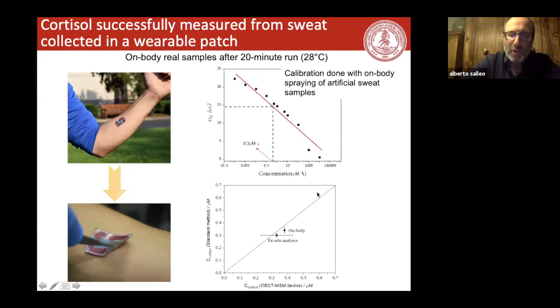And then he went out for a run, and then he measured the cortisol. So then he went back to the lab. Again, no electronics on board here, connected this to all our electronics, measured based on this calibration curve how much cortisol he expected. Then he took the sample and measured it ex situ, still with our device, but not on his body. And then he also measured it by ELISA, which is a standard method. And you see our measurement is off by maybe 20, 30%. So we're not that far off. So this is quite encouraging for a first attempt of a measurement of cortisol on body from sweat.